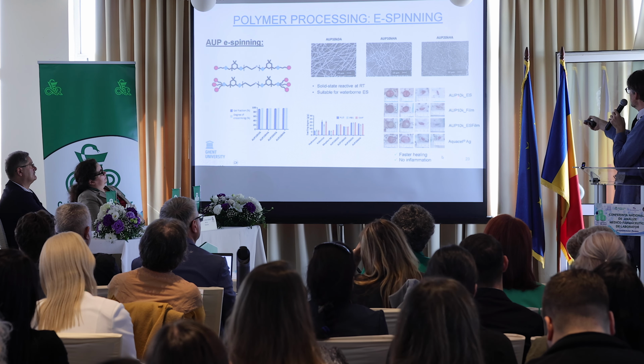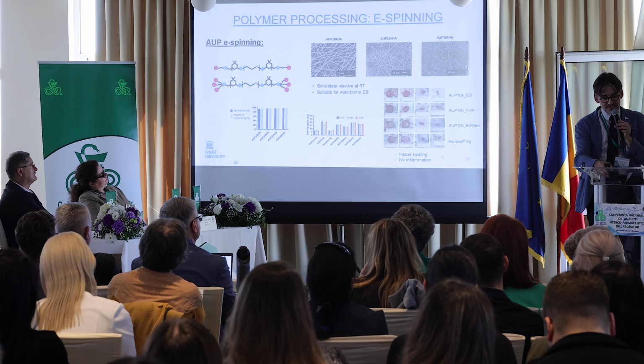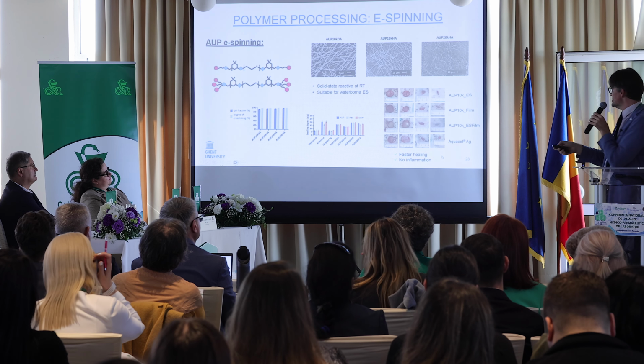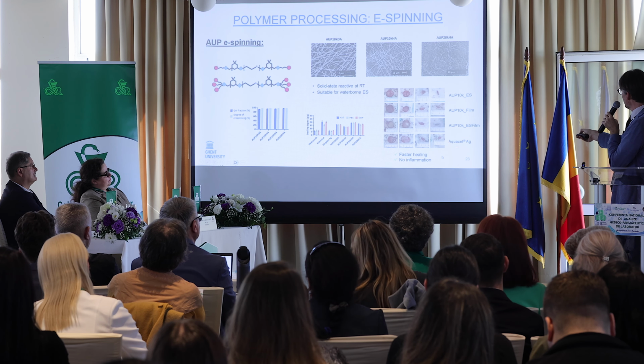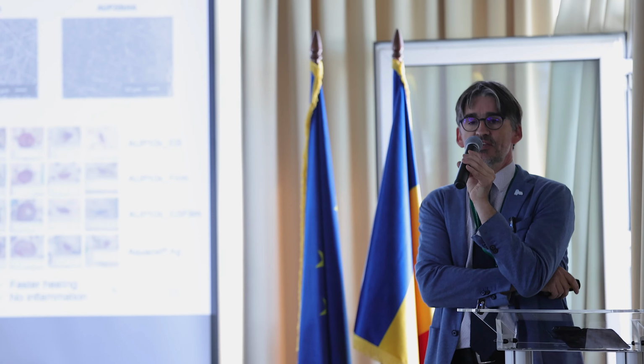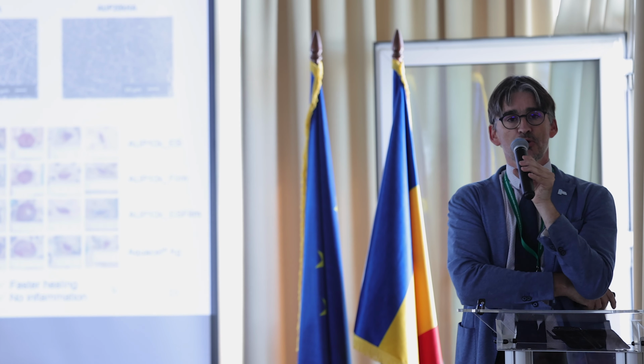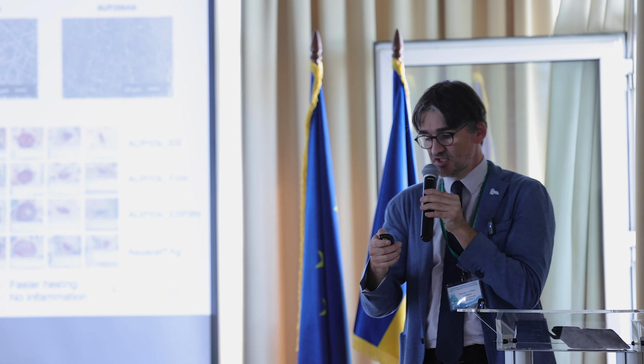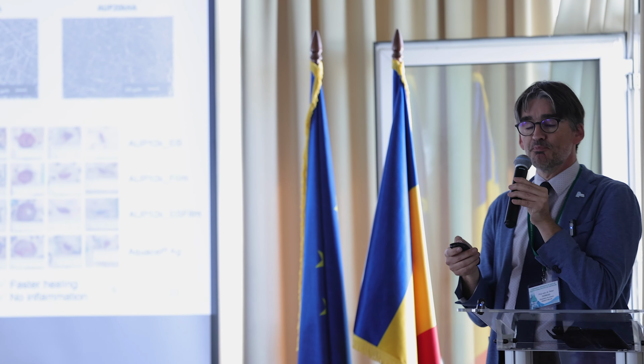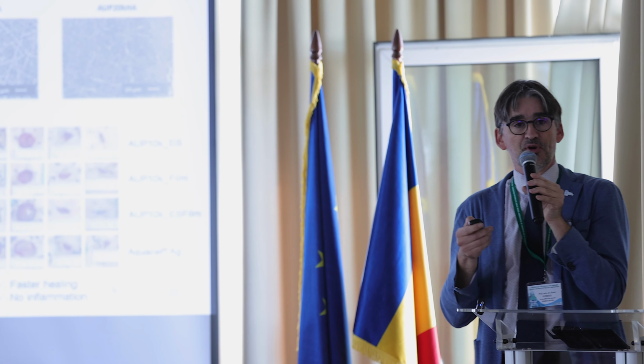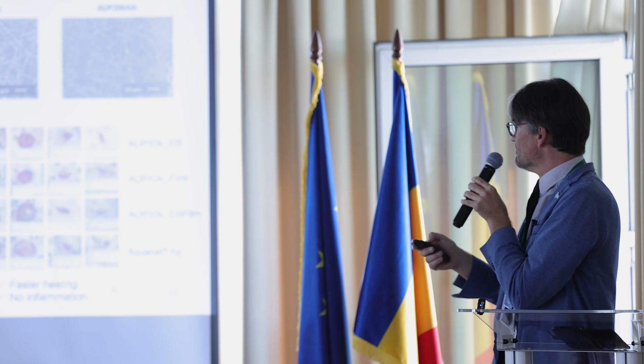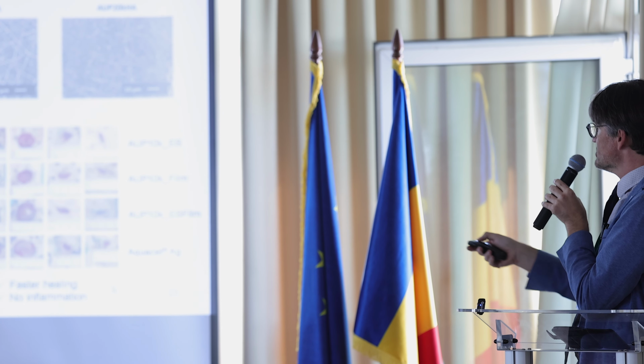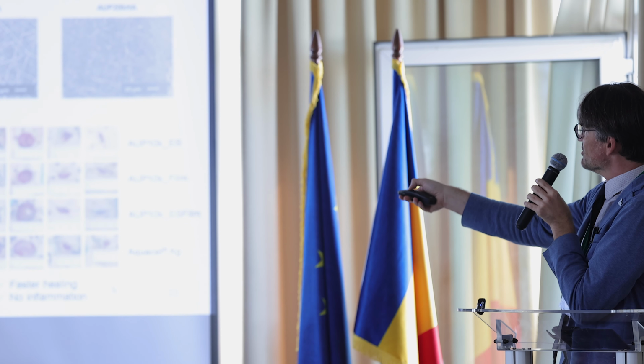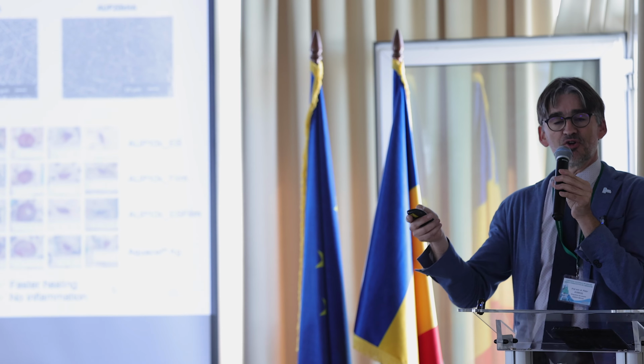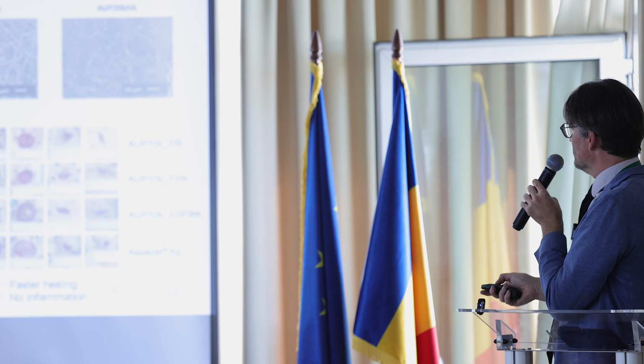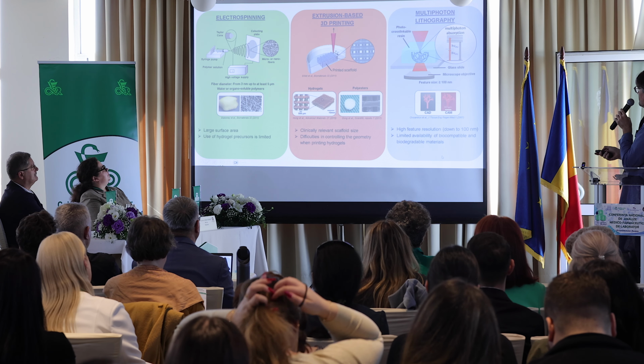Together with a local university here, we have been studying in an in vivo trial to see whether or not some of our materials can indeed stimulate the closure of certain wounds. And what we could show, as compared to a reference like Aquacel, is that our material heals at the same pace or somewhat quicker than the classical reference materials, and that no important signs of inflammation are present when these hydrogel building blocks are being developed. And again here, different types of materials were evaluated. If there's a further interest in that, we can easily continue the discussion later on.